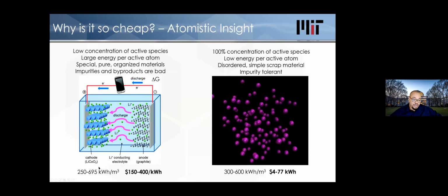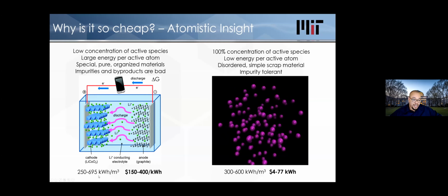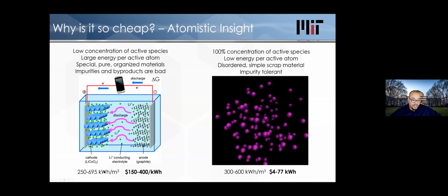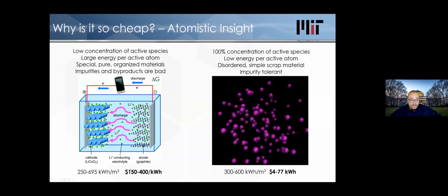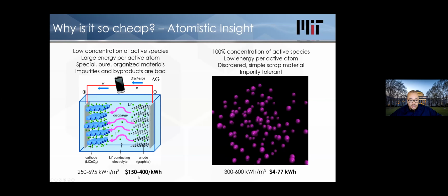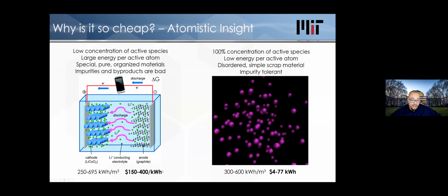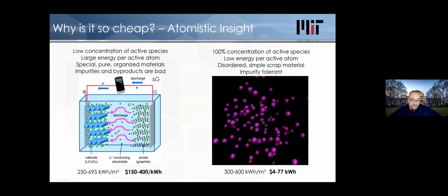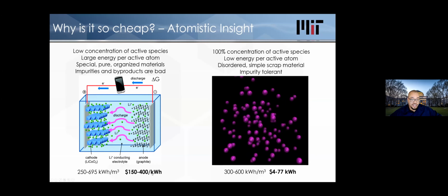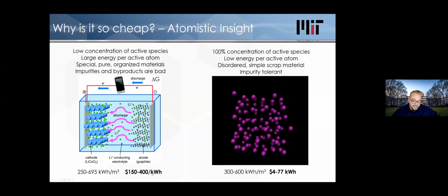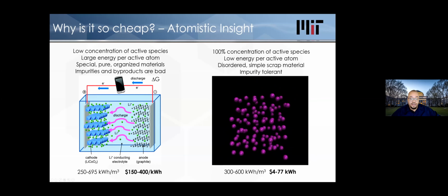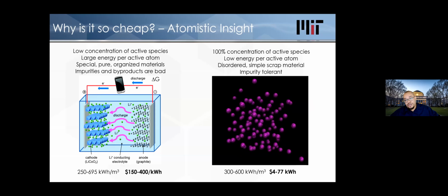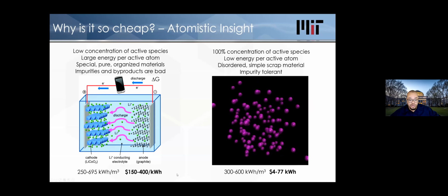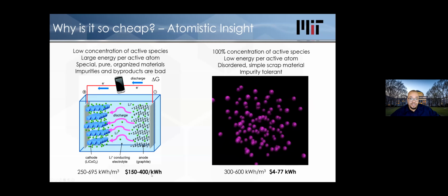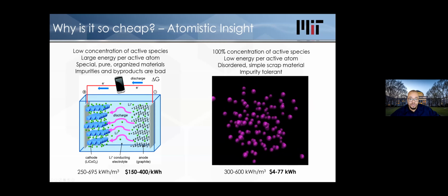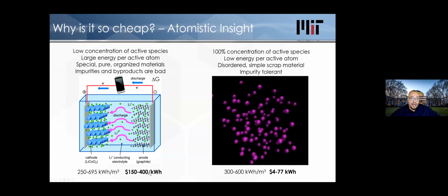If you do this approach, you get pretty great volumetric energy densities on the order of a couple hundred kilowatt hours per cubic meter. You can end up with costs in the range of hundreds of dollars per kilowatt hour. There are reports or arguments that you may be able to get this down to like $50 a kilowatt hour. However, some of the more recent studies that have looked at what costs we need to get to enable full penetration of renewables say we have to get down to like $10 or $5 per kilowatt hour. So very, very low cost, too low for batteries.